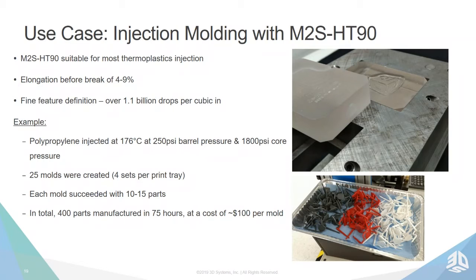For all of these applications, the HT90 offers the 90 degrees HDT, which is suitable for most thermoplastics with an operating melt temperature of between 140 to 200 degrees C. This means that you can typically injection mold plastics like polycarbonate, polypropylene, ABS, acrylic, PVC, and some other plastics as well. As we mentioned before, the elongation at break of 4 to 9% gives you the flexibility to bolt these tools securely into place, and also to remove the final injected parts without breaking the tool. And that fine feature definition, 1.1 billion drops per cubic inch of the part, allows you to create and maintain even the smallest details of the parts that you're actually intending to inject.